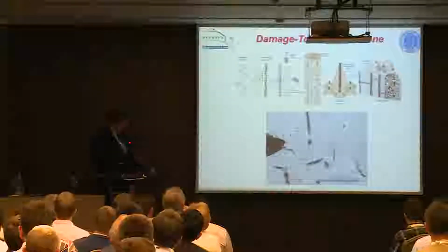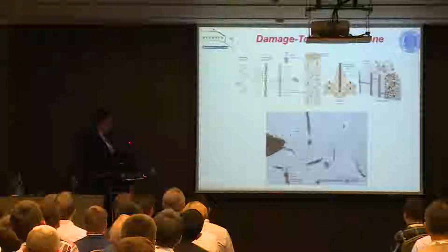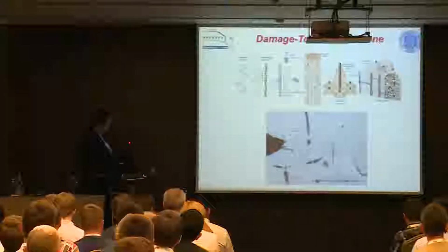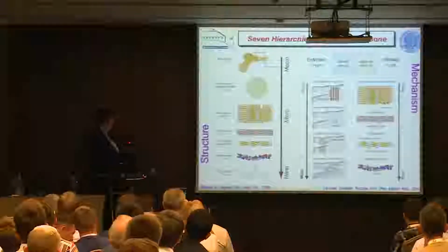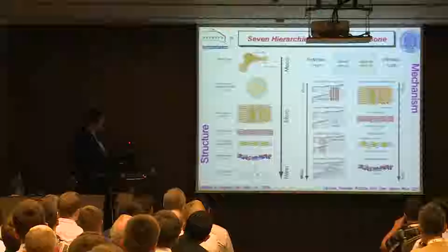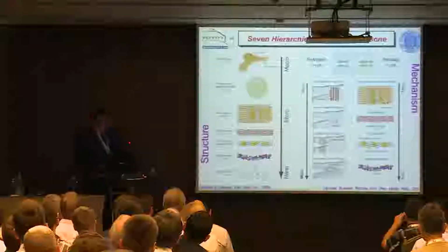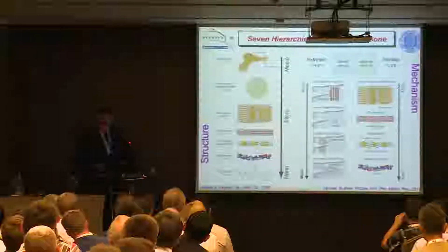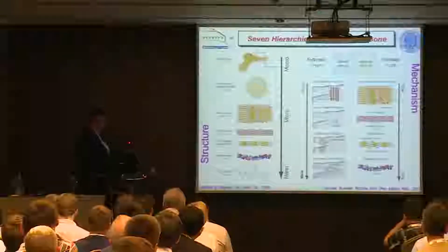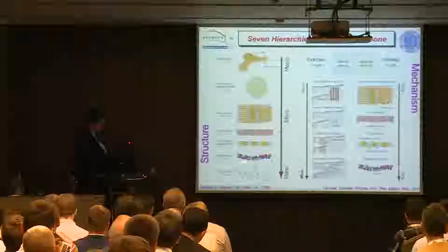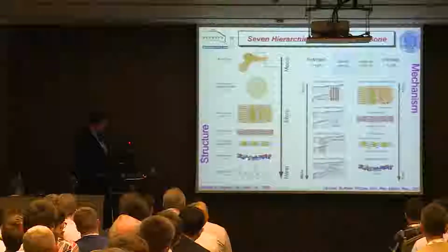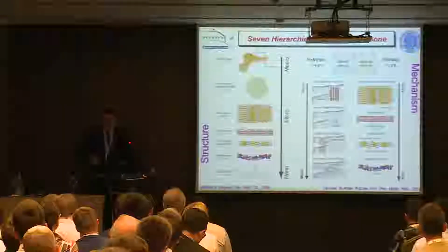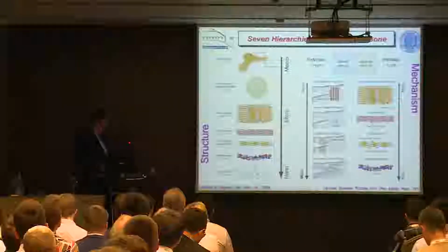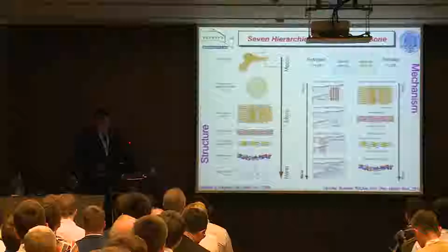So to start with, let's talk about bone. Bone is a pretty complicated material, but it's a rather remarkable material, and of course it does have a lot of length scales. A simpler way of looking at this perhaps is to go to what Weiner and Wagner did a few years ago, the sort of seven hierarchies of bone. Down here we're talking about collagen molecules that are twisted together to form collagen fibrils. This takes us into the submicron from the nanometer stage. These have minerals deposited on them, apatite, at a fairly regular, I think it's 64 nanometers apart.